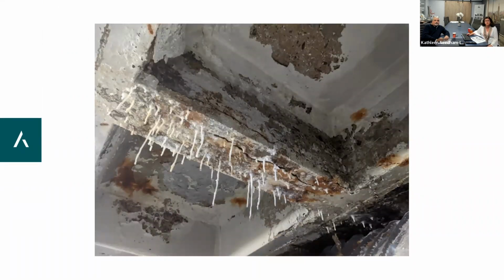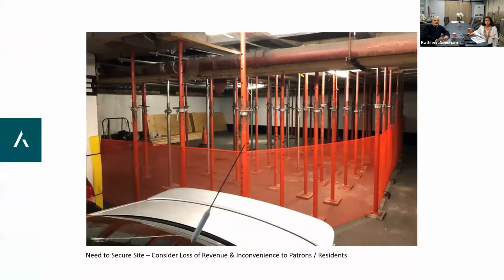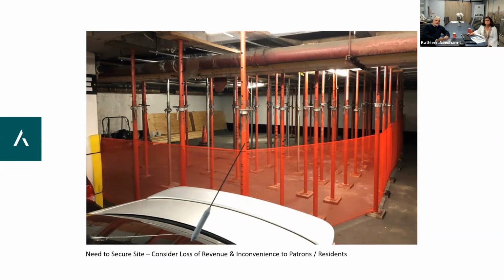You can see how long this water was leaching through the system, absolutely corroding the steel reinforcement within. So we vacated just a portion of the garage and installed these temporary columns to support the slab. So this was the ramp underneath the main ramp above. So it was very important to add stability.